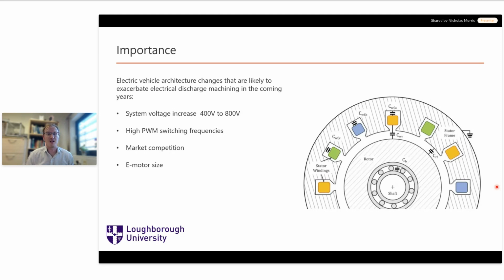Then we also have capacitive currents, and these are also called electrical discharge machining currents. And these result from the 3 phases passing through the windings not instantaneously summing to 0. And this causes an instantaneous common mode voltage between the rotor body and the frame. These common mode voltages change quickly with time, so we have a high rate of change of voltage with time, dV by dt, and this means that we can drive high capacitive currents across the junctions that you can see here.